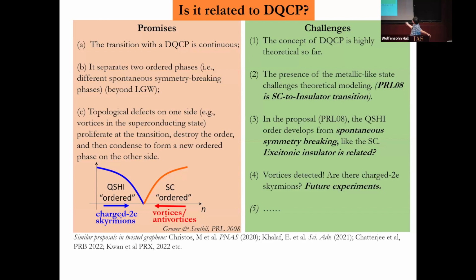The challenge is that this so-called deconfined quantum critical point is still very theoretical at this moment, and there's a metallic state there. In the pure theory, they don't want a metallic state because they don't know how to deal with it. There are too many gapless excitations, and they need this quantum spin Hall insulator, not a trivial band insulator, where you don't have spontaneous order developed, right? Which is actually very relevant in our case because, as I mentioned in the beginning, we have an excitonic insulator. The quantum spin Hall insulator we have is not the single-particle quantum spin Hall. It's excitonic, there might be excitonic order and so on. So there is indeed something encouraging here to think about.